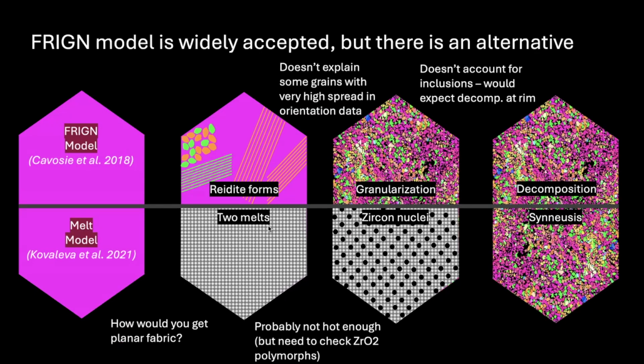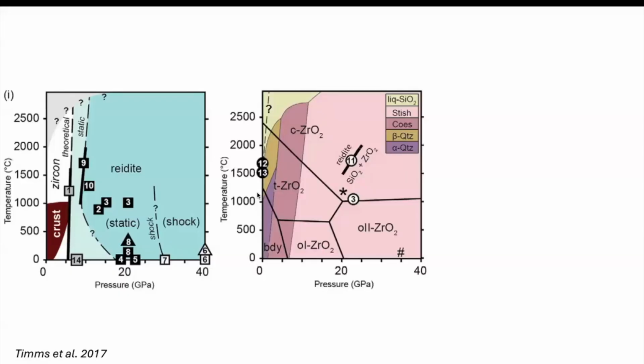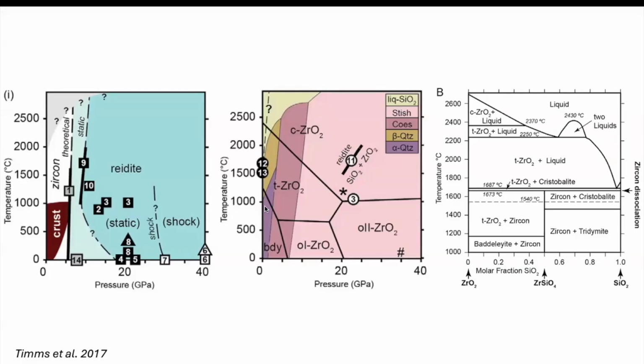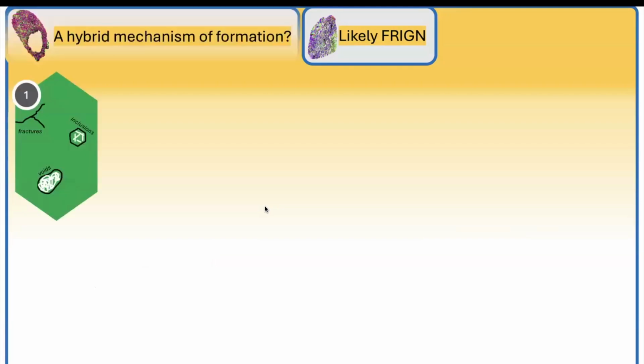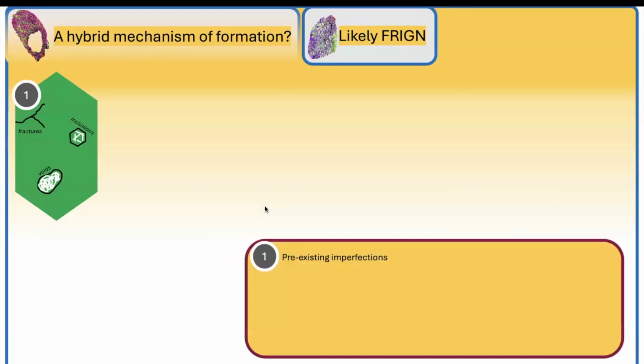It's probably also not hot enough to melt zirconia. And there's not necessarily enough time for the synneusis process where the grains grow large and rotate and adhere to minimize surface energy. So thinking through these phase diagrams, we said this one was likely FRIGN, but I have a different idea for the second grain. So I'm thinking a hybrid mechanism of formation. We start out with some pre-existing imperfections in zircon.